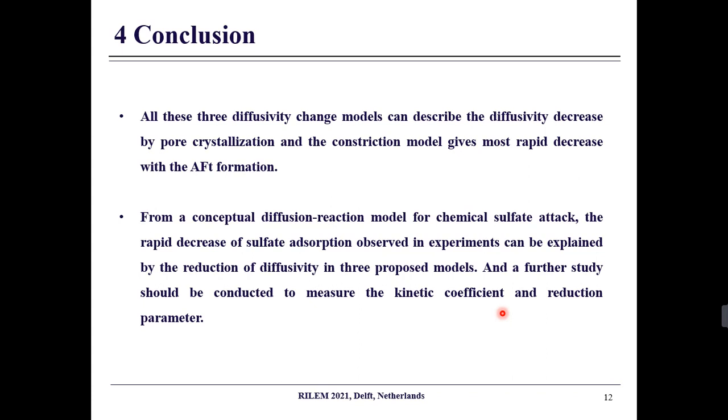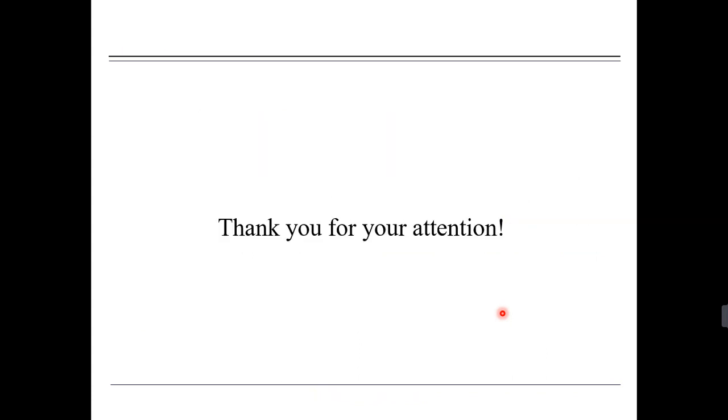Secondly, from the conceptual diffusion reaction model for chemical sulfate attack, the rapid decrease of sulfate adsorption observed in experiments can be explained by the reduction of diffusivity in the three proposed models, and further studies should be conducted to measure the kinetic coefficient and reduction parameter. That's all. Thanks for your attention.